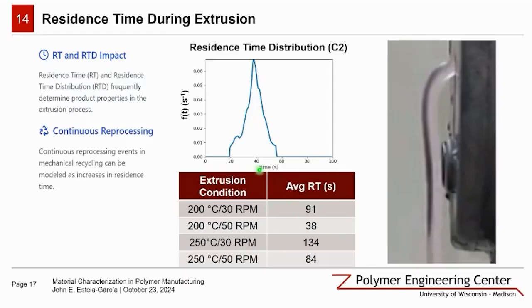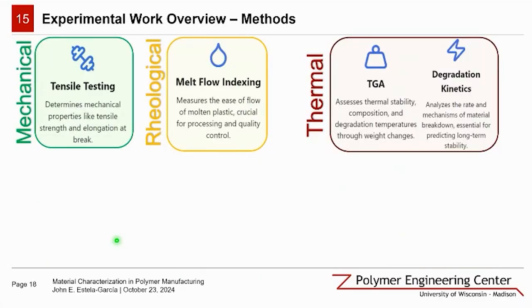So residence time and its distribution, what we're observing here, are key determinants of product properties and extrusion process. They influence the degree of mixing, the extent of reactions, and ultimately the quality of our final product. In mechanical recycling, we can model continuous reprocessing events as increases in residence time. This approach allows us to draw direct connections between processing time and property degradation. By fine-tuning residence time, we can potentially extend the number of times a material can be recycled without significant loss of properties. So let's kind of focus on some of the experimental methods that we're applying.